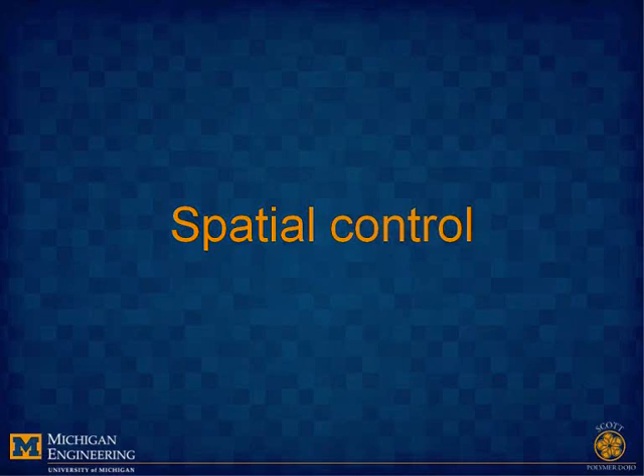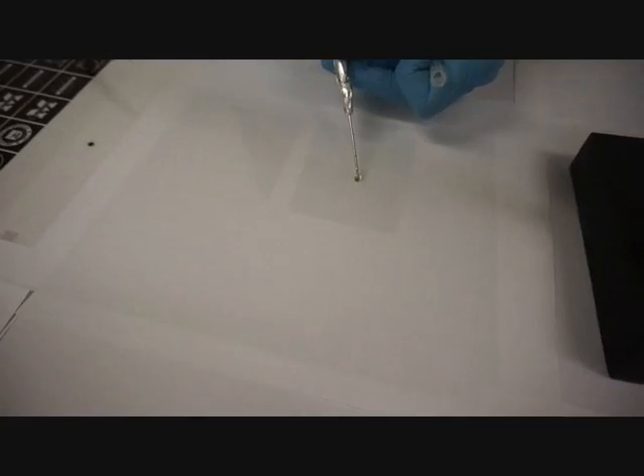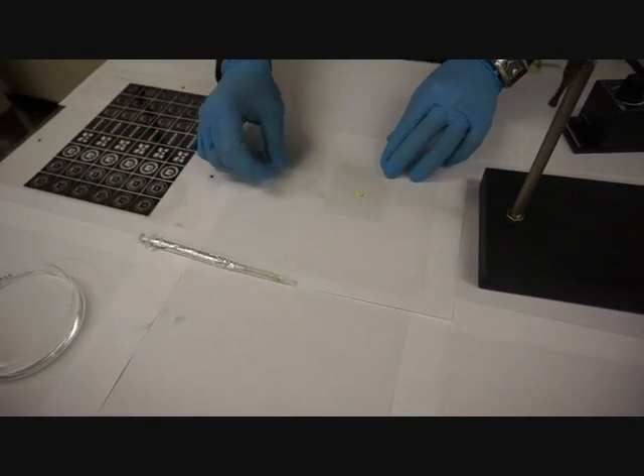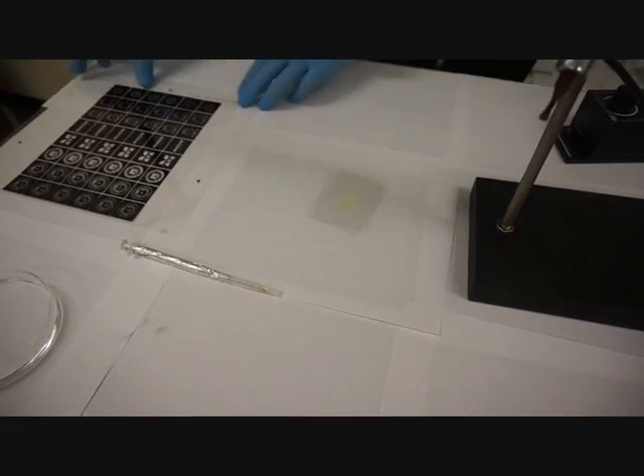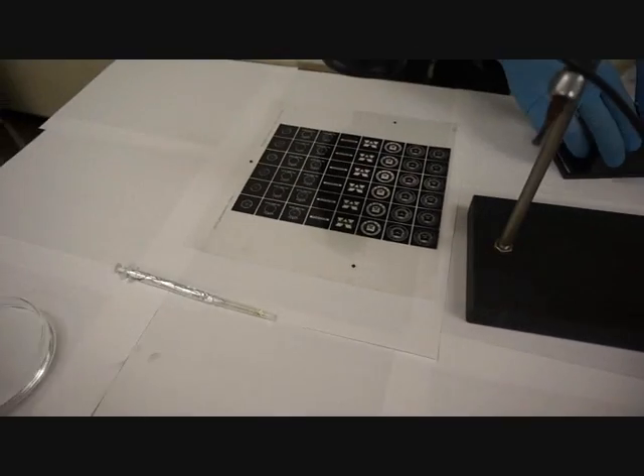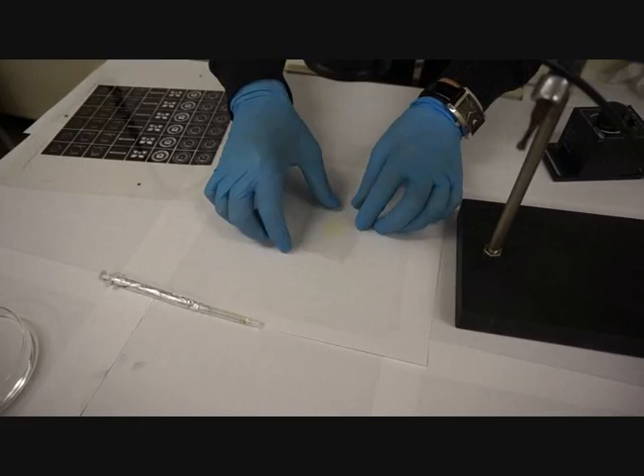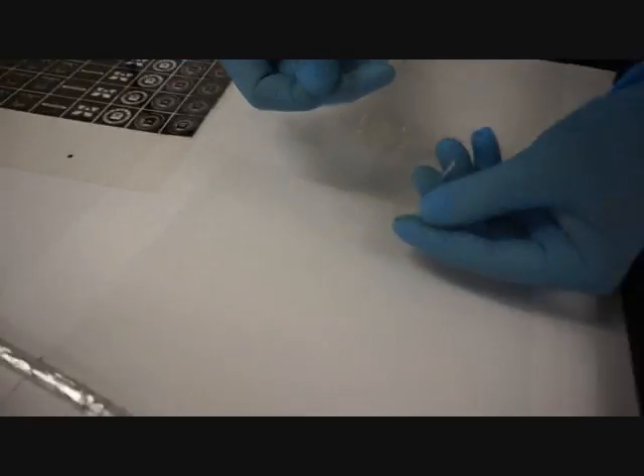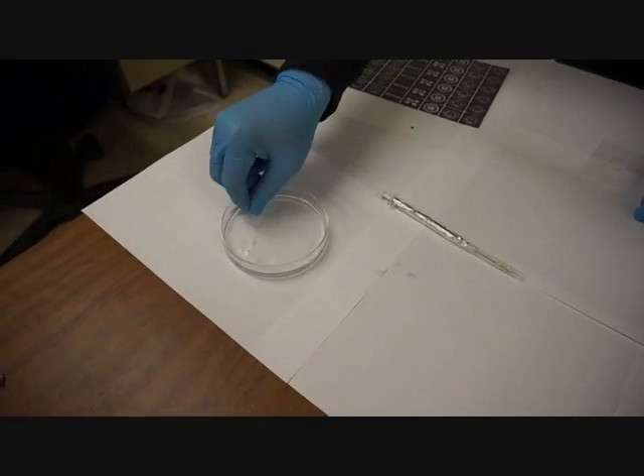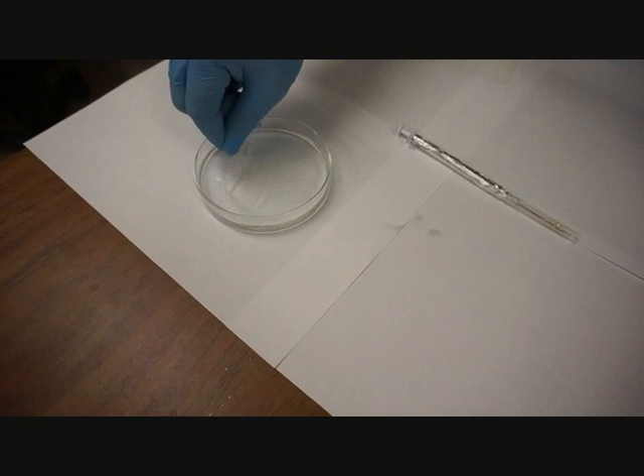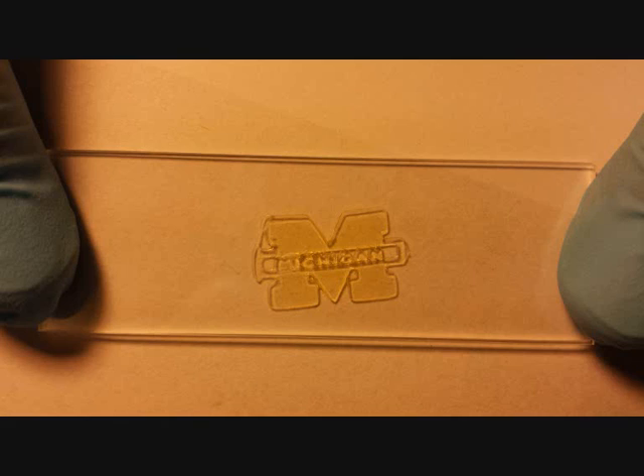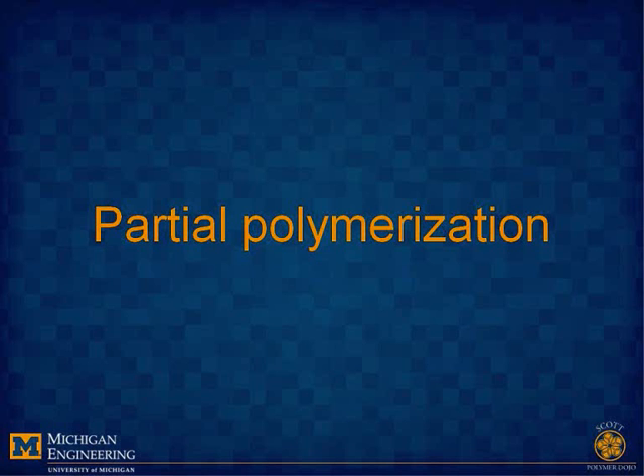To demonstrate spatial control, coat the thiol-ene resin between 2 surface-treated sheets of PET so that the cross-linked film can be peeled off later. Cover the coated surface with a patterned photomask and irradiate the exposed surface for a couple of seconds. Since the unexposed resin does not cross-link, it can be washed off with acetone to produce patterned adhesion for intricate applications. An interesting ability of these resins lies in their partial polymerization.